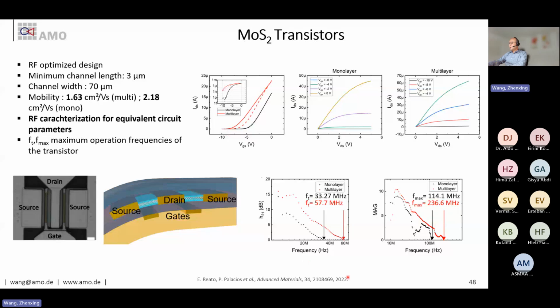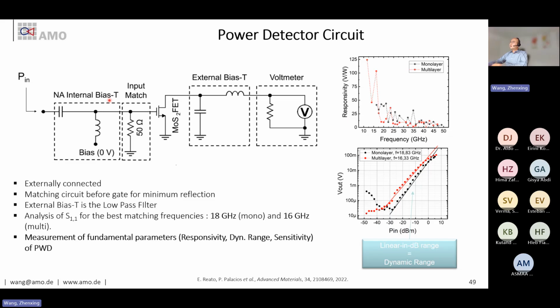I want to show here work from 2022, in which we demonstrated a MoS2 transistor that can work on a flexible substrate, showing frequency response to several hundred megahertz. I know it's not good because the mobility of the MoS2 is not good. It's only 1 square centimeter per volt second, compared to graphene's several thousand square centimeter per volt second. But people are still working on improving the mobility of such materials. And the good thing is that, as I mentioned before, we can realize the power detector even with this several hundred megahertz cutoff frequency.